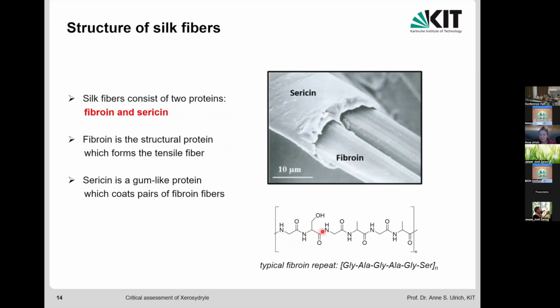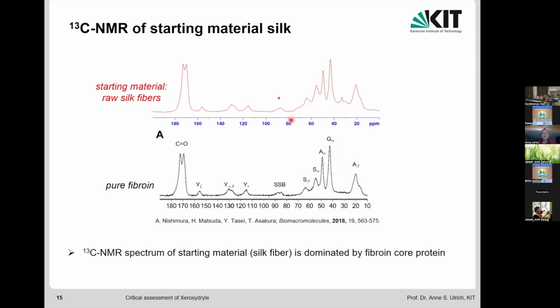This protein has an unusual amino acid sequence. It's rich in alanines, glycines, and gives unusual NMR spectra. The two core fibrils are, however, coated by another protein called sericin. And this is a gum-like protein which makes the fibers a bit sticky so that the silkworm or spiders can make their nets. And now we can look at the separate NMR analysis of sericin on the outside and fibroin on the inside, because you can buy the material or prepare it yourself by washing the fiber. And here is a comparison of the raw silk fiber, the complete bulk, and the pure fibroin, this protein that gives it the tensile strength.